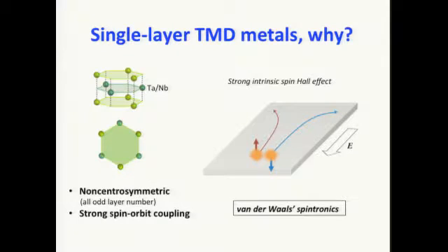Plus that, the tantalum or the niobium atoms, one is 4d, one is 5d. It has very strong spin-orbit interaction. So for a material which is non-centrosymmetric with strong spin-orbit interaction, we would expect a very strong spin-Hall effect in the material. And this is actually an interesting direction because it may give rise to a large spin-orbit torque effect in spintronics devices.